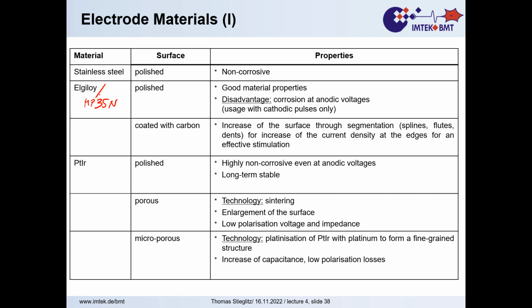The standard material still is platinum iridium, and this table is strongly linked to cardiac pacemaker electrodes with the statements there. Platinum iridium is very good, highly non-corrosive, long-term stable, but it still corrodes. Yeah, there's nothing that does not corrode. And the statements have been made in textbooks at a time where people did not look that carefully into that. Since 2 years, there are the first long-term studies on corrosion of cochlear implants. So explants have been carefully investigated, and you can easily see that platinum iridium corrodes over 25 years under permanent stimulation. So that means some redesign rules will be a bit more focused on that.